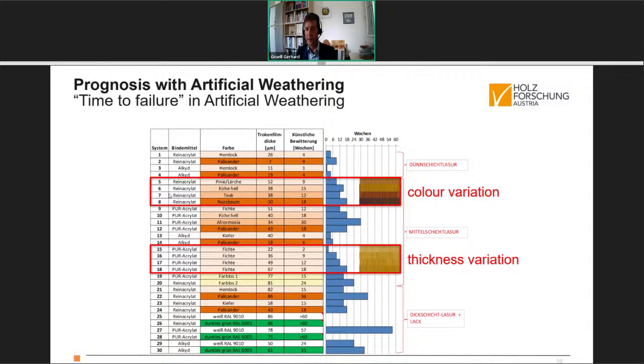Interesting groups in this sample plan were 2 variations of the same products. The first one in color, which is this group here, and you see that these varnishes with darker pigmentation lasted longer than the ones with brighter pigmentation, which is seen here. And another nice variation was the film thickness variation of the same coating material, which again gave a nice stepwise behavior in terms of time to failure in artificial weathering.